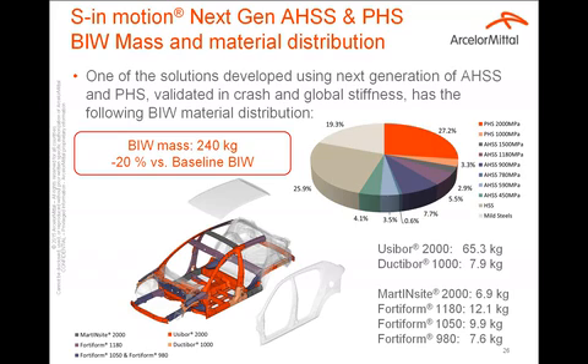We also have Ductibor 1000 combined with Usibor 2000, especially with laser welded blank application. And more than 16% of 3rd-generation grades, 980, 1180, and 1050, as I described before, on specific parts in the different colors as explained on the body-in-white structure on the left of the slide. That represents more than 70 kilograms of new press hardened steels potential, and more than 30 kilograms of new 3rd-generation family.